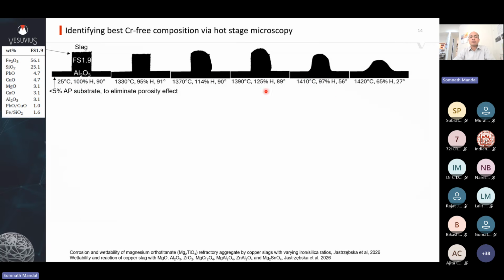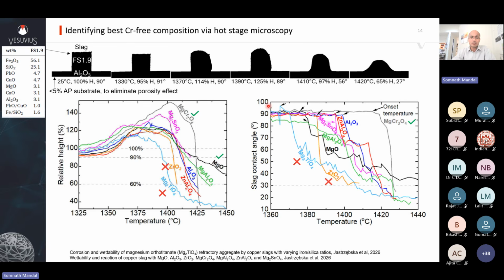So one of the nice techniques to pre-screen potential phases is hot stage microscopy. What you do here is that you have a fixed slag composition, you make a cube out of it, you have refractory substrates, and then you heat it and you observe the evolution. And what you observe is the height change of the slag, and then you observe the contact angle at the interface between the slag and refractory. And this gives you a very nice estimate of what's going on.